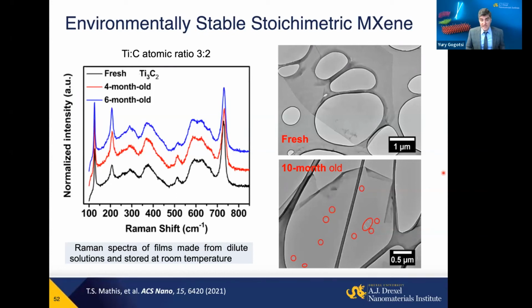And of course, they can be combined with semiconductors. There are many semiconducting 2D materials, including, say, the classic molybdenum disulfide. I think attractive is using them in combination with known semiconductors as current collectors, making couples when you match a work function, for example, that you can tune in MXene. Basically, barrier control between the layers.